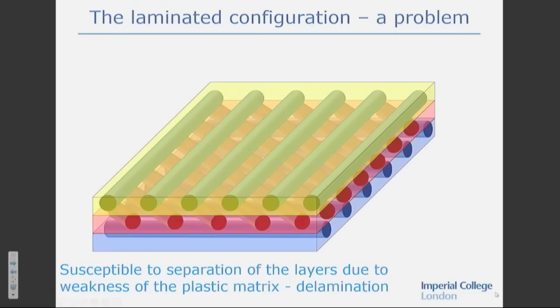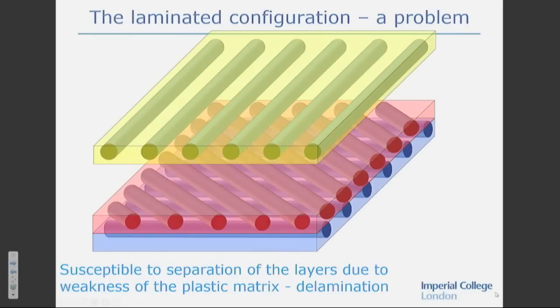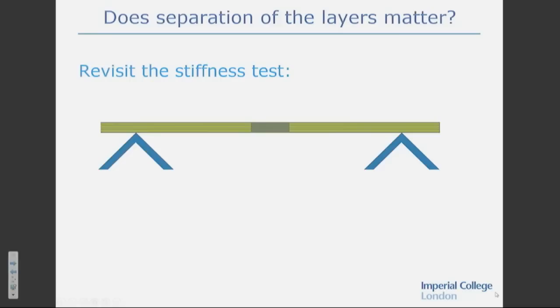But there's a problem with this. And it is that the only thing holding these strong, stiff layers together is the relatively weak plastic matrix. So each of those plies is connected to the next one only by the plastic matrix. And so it's susceptible to separation of the layers or delamination. If the loading's right, we could rip off that top layer, for example. Now, how important is separation of the layers?